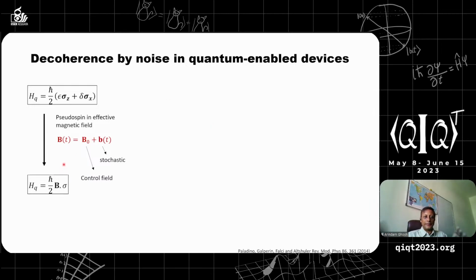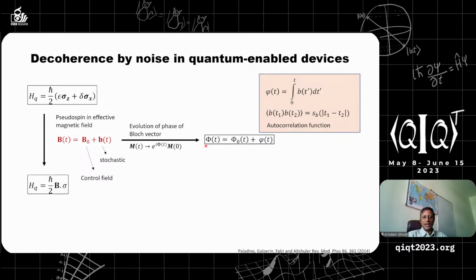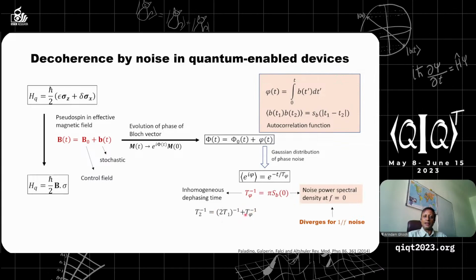Okay, why is that important for our quantum-enabled devices? Because if you look at the control field and the stochastic field that comes from these disturbances in the environment, it's not very difficult to show that the autocorrelation function of the stochastic field will cause the quantum information to decay with a time scale of tau phi. And the T2 time is now determined in certain situations by the phase breaking time, or tau phi inverse, where tau phi inverse is essentially the zero frequency power spectral density of noise. And as I said, 1 over f noise diverges. So that means that the T2 time becomes really, really small. So we do not want 1 over f noise in our systems.